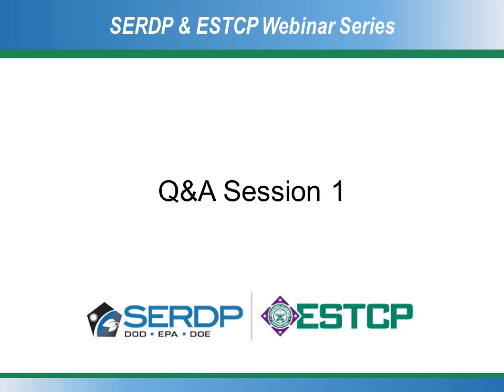Thank you. Prior to coating with your nano material, how is the surface prepared or primed? With the different materials, when we coat any material, we use a standard electroplating process. So how you would treat the material is exactly how you would treat the material for plating it with any electrodeposited coating. For example, steels typically go through a pickling step to remove the oxide.